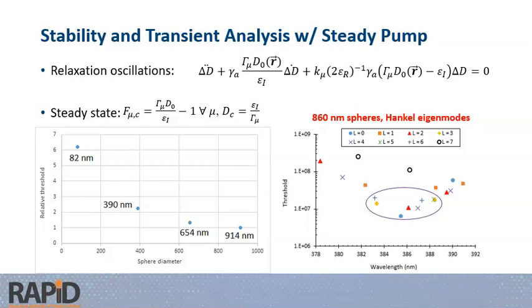We've been able to do this with polydisperse zinc oxide nanoparticles, so we haven't had to rely on Mie scattering from a monodisperse set of nanoparticles outside the sphere. This is in contrast to some earlier results where they had to rely on monodisperse nanoparticles with Mie scattering. Here we're not doing that, so it's much easier to coax emission from these systems and still get down to single mode lasing. You can see here on the left graph there appears to be a threshold reduction as you get to larger spheres, so you have another lever to control the threshold in the system.